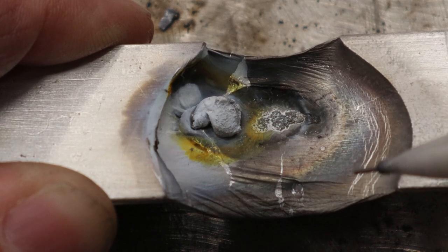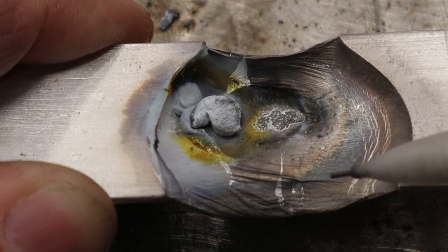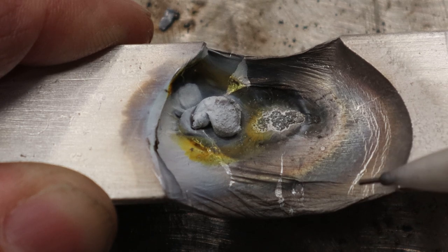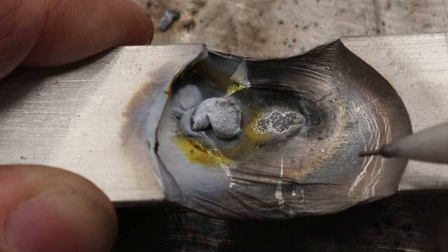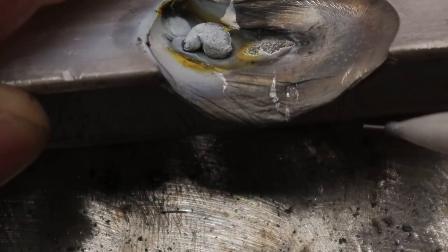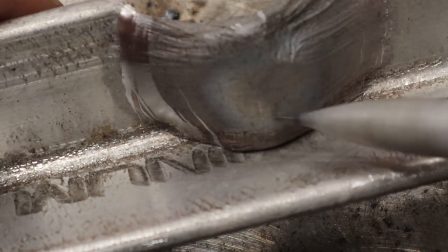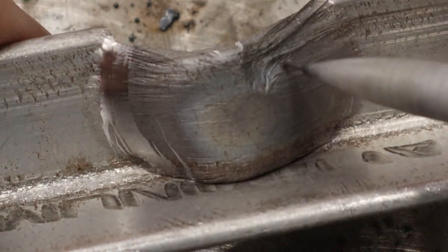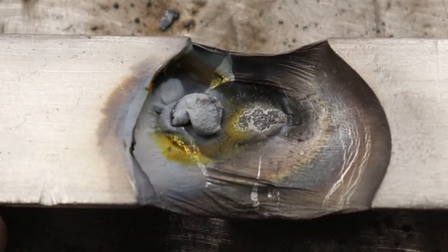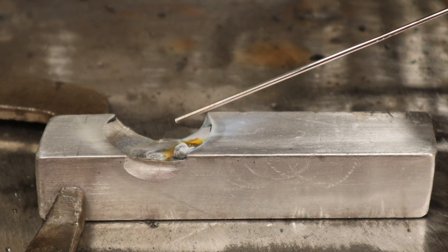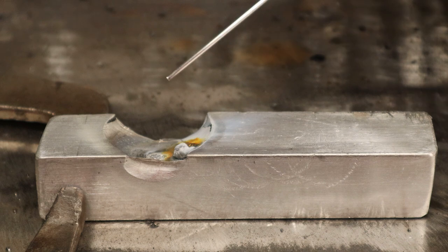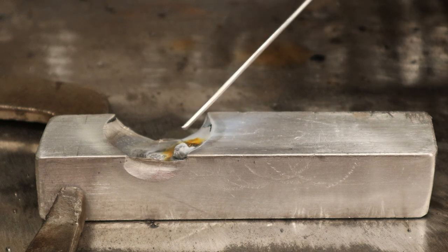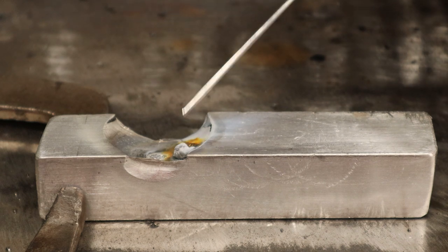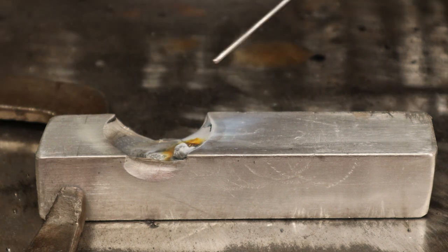And that was that aluminum oxide that does not want to get melted yet. However, there's lots of heat going in. So with DC negative, all the heat is going into the material. And so the inside that's melting at 600 degrees Celsius literally started to melt and sag and fall away from me. And even when I took some aluminum and started adding it with my filler rod, it did not want to stick. It just balled up because there's a lot of aluminum oxide on it as well. And no puddle, so no welding.